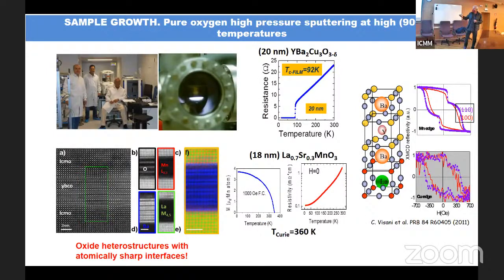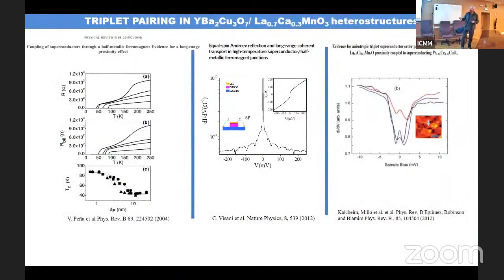What we do is we grow these materials using this non-standard high pressure sputtering technique in pure oxygen and 900 degrees temperature, right? In single films, it produces fantastic materials and also heterostructures with very atomically sharp interfaces. And the reason to choose these materials was because over the years, we had quite convincing fingerprints that these triplets might exist in this system.